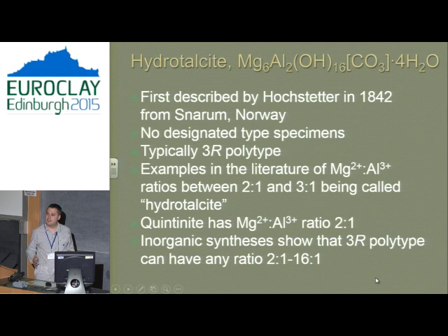Everyone's always thought that hydrotalcites were typically the 3R polytype, but if you go and have a look at the literature going back all the way from the 1800s through the early 1900s when people like Frondell were first looking at hydrotalcites and then extended into modern mineralogy, we have examples of things being called hydrotalcite that have a 2-to-1 ratio and a 3-to-1 ratio. So in mineralogy, when you have different ratios like this, they can't be the same mineral. So we went, uh-oh, does hydrotalcite really exist? Because if it has a 2-to-1 ratio, it's a different mineral than if it has a 3-to-1 ratio.